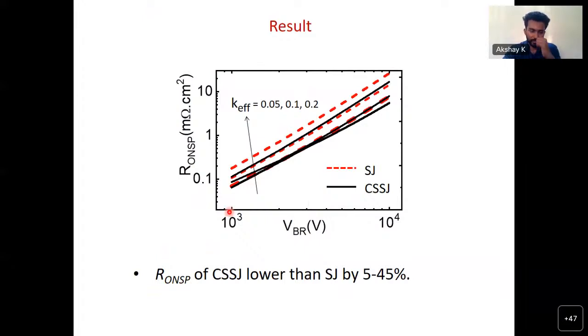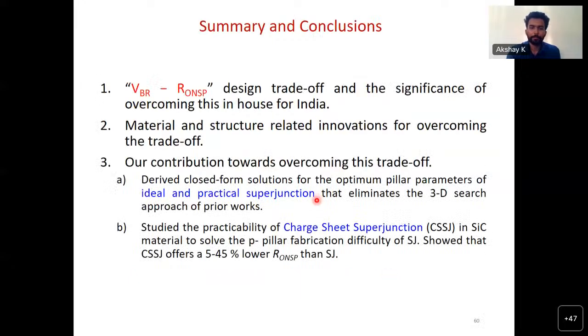These are some of the calculations using our model, comparing the specific on resistance for different breakdown voltages from 1 kV to 10 kV of superjunction and charge sheet superjunction, and we could demonstrate that our proposed device could lower the on resistance by 5 to 45%. So that's it. And then in conclusion, we discussed the breakdown voltage specific on resistance design trade-off and its significance in overcoming this in-house for India. We also saw material and structure related innovations for overcoming the trade-off. Also, we discussed the contributions that we could give from our research work towards overcoming this trade-off.